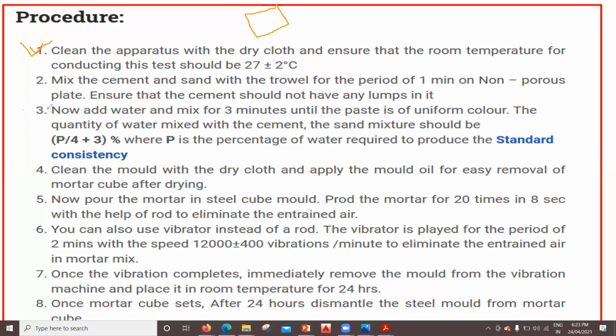The third point is that now we need to add water, right? Now add water and mix for 3 minutes until the paste is of uniform color. The quantity of water to add to the cement and sand mixture, as a percentage, is P/4 plus 3%, where P is the percentage of water required to produce the standard consistency. And if you remember, we had got it as 35%, so you add 35% divided by 4, plus 3%. Next, clean the mold with a dry cloth and apply mold oil for easy removal of the mortar cube after drying. So whenever we clean the mold, after that we need to apply the oil, right? So why do we have to apply the oil?